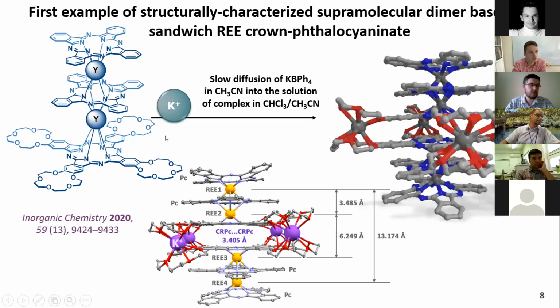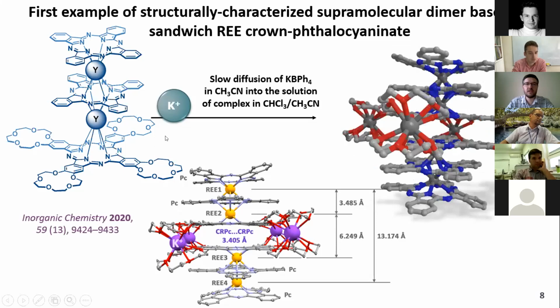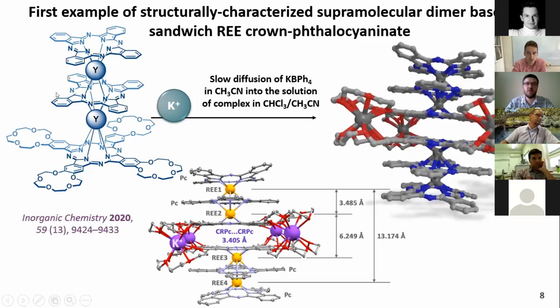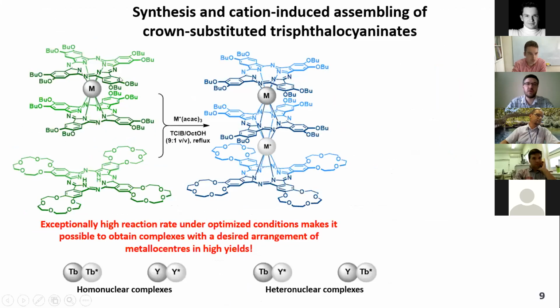So to improve the stability of this complex, we decided to introduce electron donor substituents into the non-ionophoric phthalocyanine ligands, and we chose butoxy groups as these electron donating substituents. And thus we developed an approach to synthesize such triple decker complexes containing one terminal crown substituted ligand. It took us a lot to find optimal conditions to synthesize it, but finally the best conditions are written here.